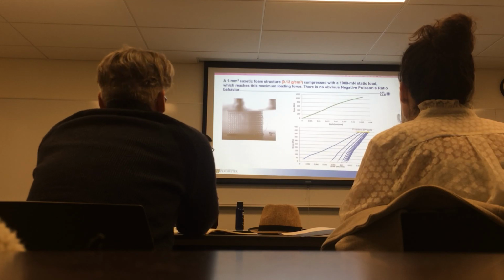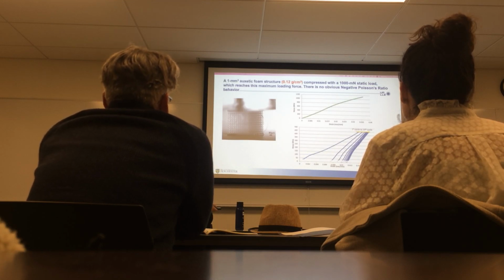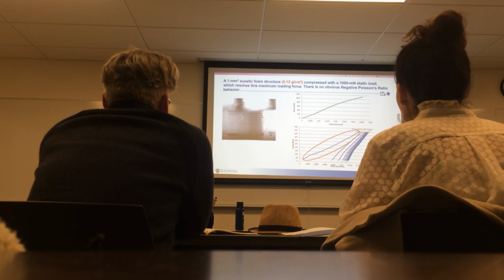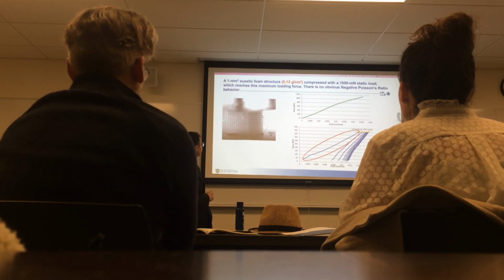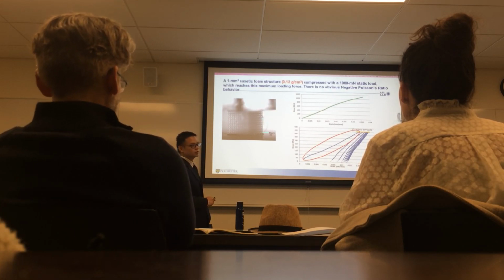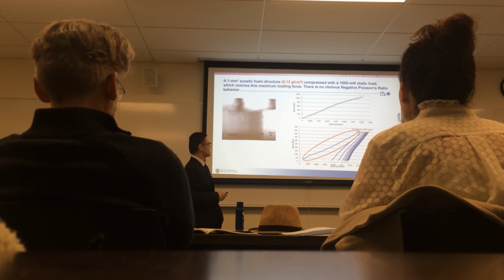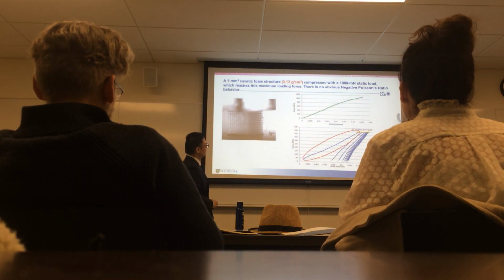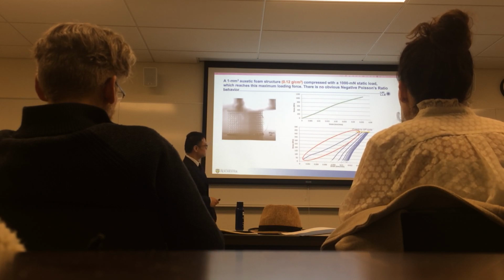For the foam structures, we use the crush compression test. At first, we used a 1 cubic millimeter foam structure for the compression test. We applied 1,000 millinewton force on the top surface, which is the maximum force for the equipment. But we didn't see the negative Poisson ratio behavior. We didn't see obvious shrinkage in the vertical direction, and we didn't crush these structures. The first foam structure was just like our preliminary test, so it helped me improve the experiment process.